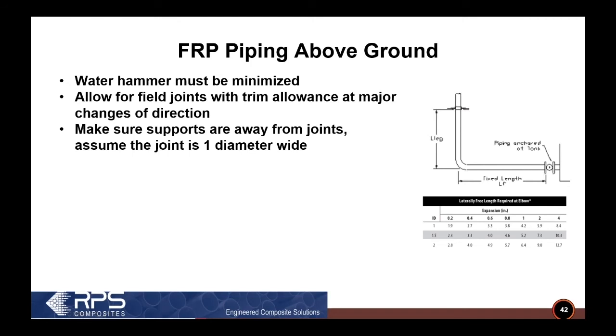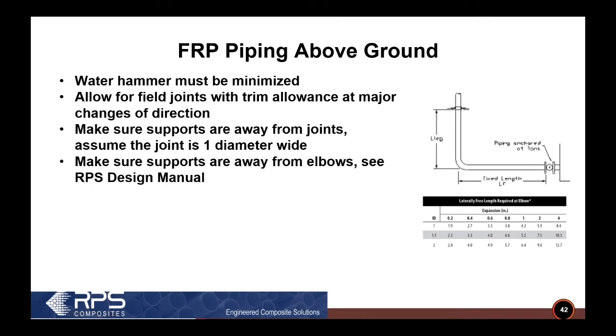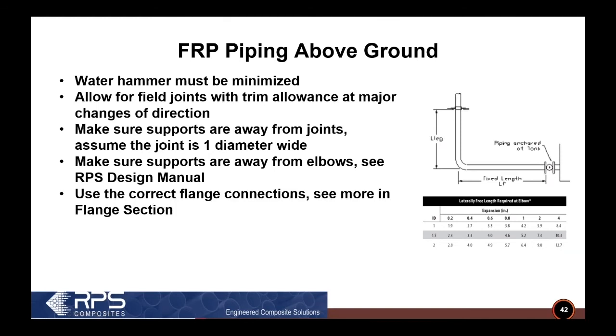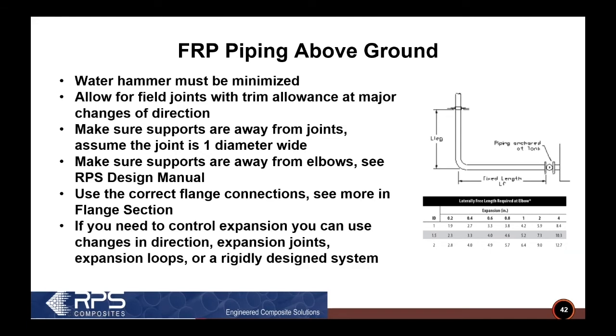You got to make sure your pipe supports are away from your joints. And again, you can assume that those joints are going to be about a diameter wide. And you got to keep the pipe supports also away from elbows, and you have to have this lateral free length. There's some guidelines in our design manual of how to do that. And very importantly, you got to use the right type of flange connections when you're dealing with above ground FRP pipe, and I'll tell you a little bit more about that later.